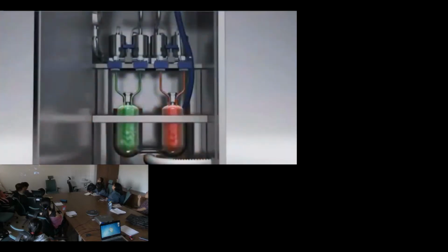Yeah, so the hafnium chloride gas goes everywhere. It also goes inside the wire. And on the surface, you can see some very first reaction. So we have the hafnium chloride gas molecules attaching to the surface, also by chemical reaction. So what is important here is that this surface should be hydrated in order to form bonds with the molecules.